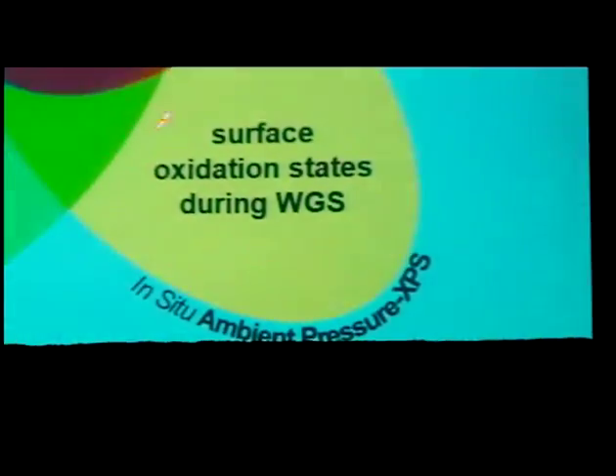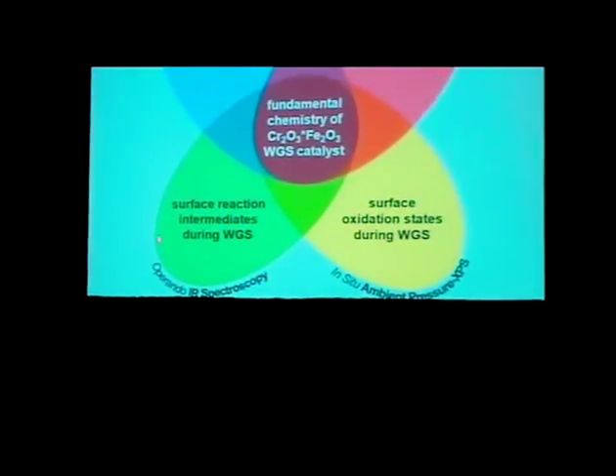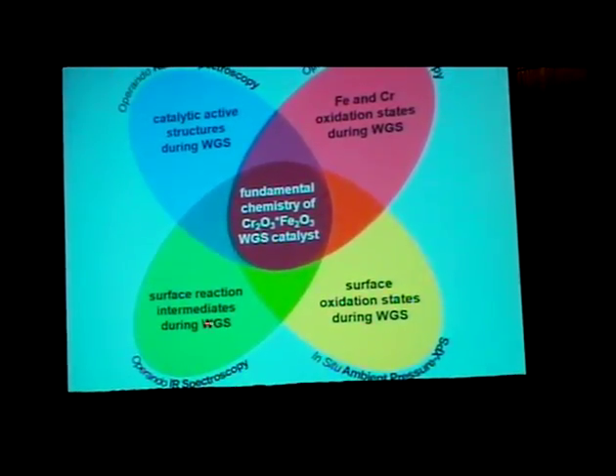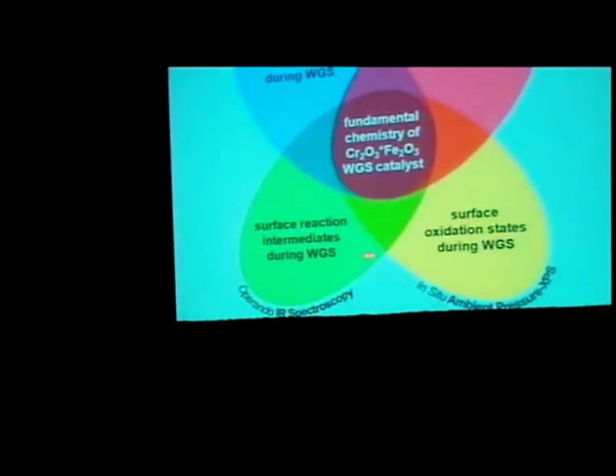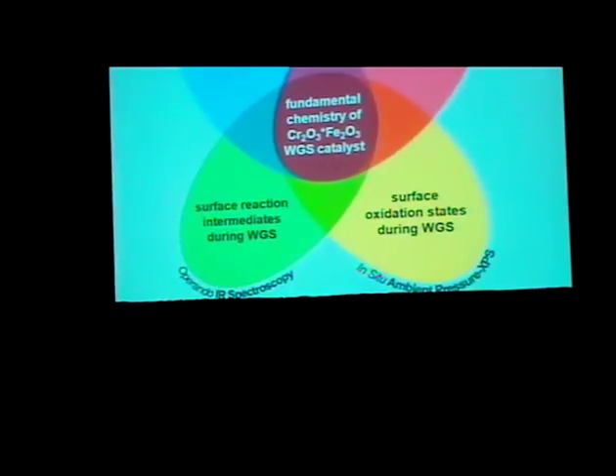Particularly for chromium, we turned to in situ ambient pressure XPS. This is Franklin Tao's laboratory. Yes, the only, to my knowledge, lab scale instrument that's able to do this in the USA. And to get information about surface reaction intermediates during the water gas shift, we turned to operando spectroscopy to be able to see what's on the surface.